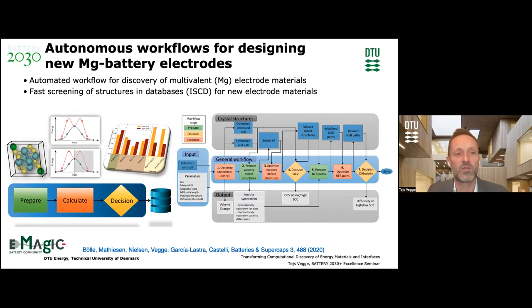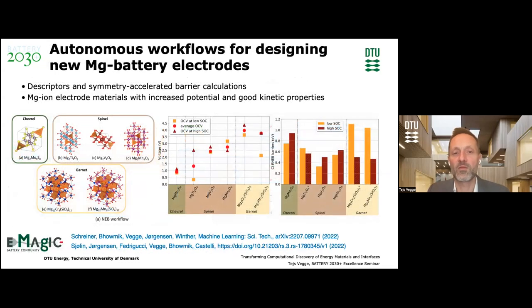Automatically, he could screen potential structures and candidates and generate simulated structures that would allow him to map out the expected potential at low and high state of charge, but also in a systematic way assess the transport kinetics. So actually do an accelerated procedure for assessing the kinetics of an electrode without having to synthesize and test the electrode. What came out of this specific study was that a number of different structural motifs were identified as having potentially interesting candidates.